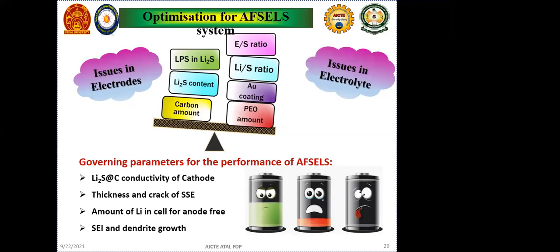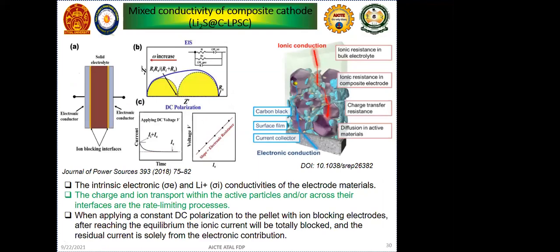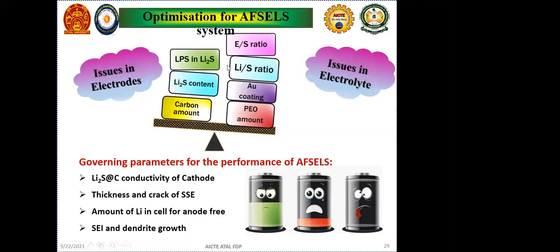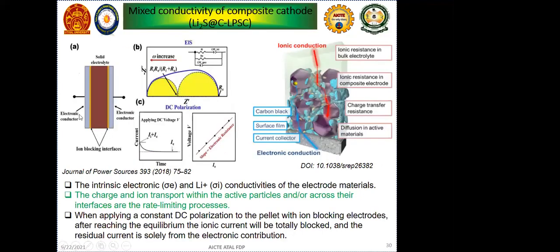So my strategy is that we can focus on using this lithium sulfur cathode with carbon, and we can focus on thickness or cracks of the SE, and also the amount of lithium in the anode free battery, and then focus on solid electrolyte and anode free. As I just said, the mixing of this LPS and Li2S is a major factor. So this factor can be governed by how much Li2S we are using, or how much carbon we are using, or how much LPS we are using to develop the cathode.